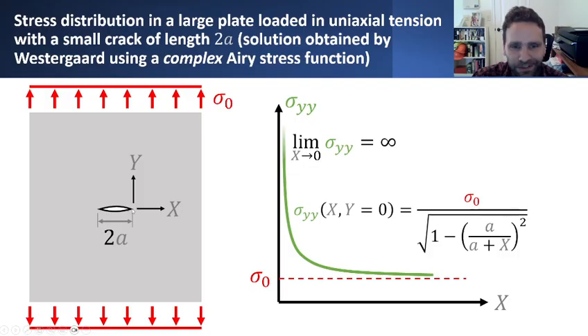And he came up with a solution that looks like this, looking in particular at the YY component of stress, the normal component of stress in the direction of the applied tensile loading. You can plot the variation in the YY stress as a function of X relative to the origin here. Further away from the crack, the stress levels out and asymptotically approaches the far field state of stress, as we would expect. That's in agreement with the solution we looked at previously for the plate with a circular hole. There too, in the far field conditions, as you move further and further away from the hole, you approach a state of uniform stress in agreement with the far field stress conditions.